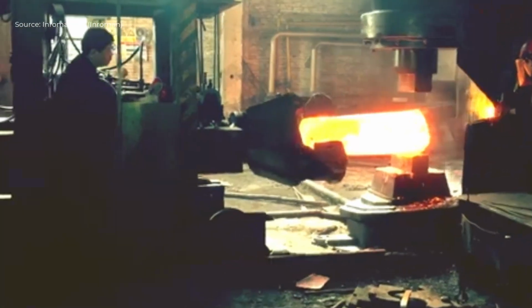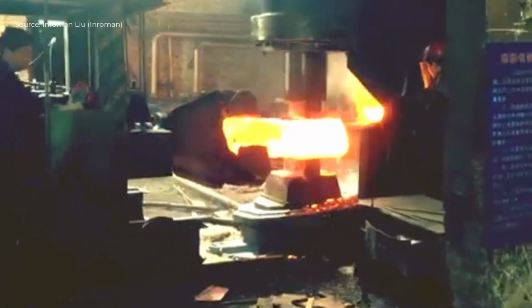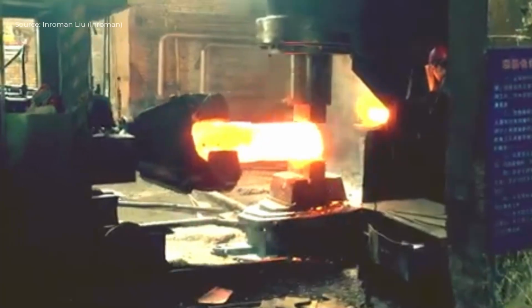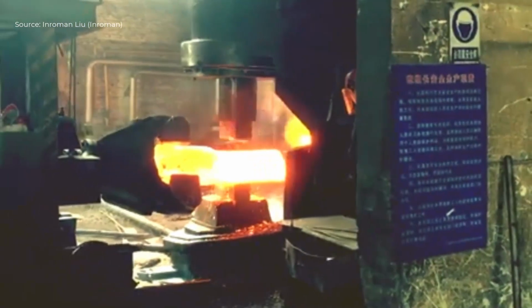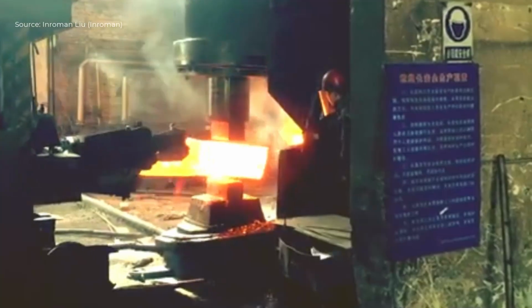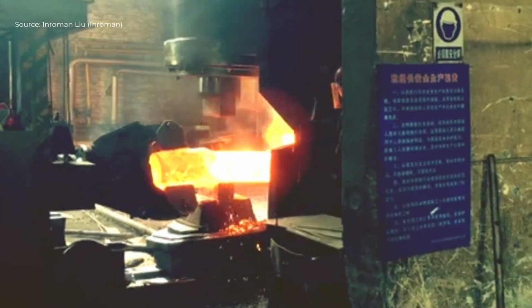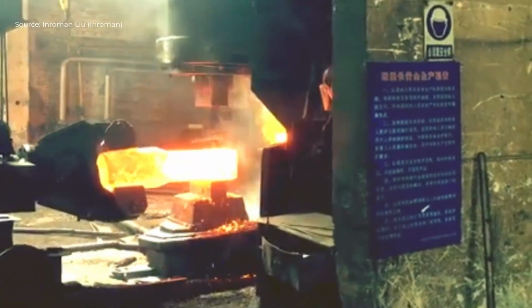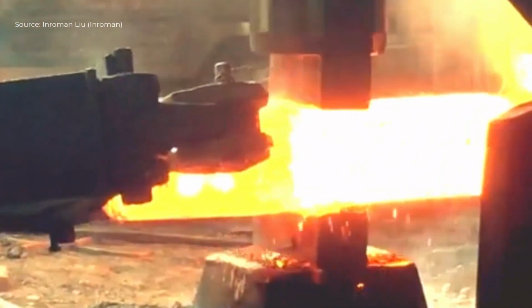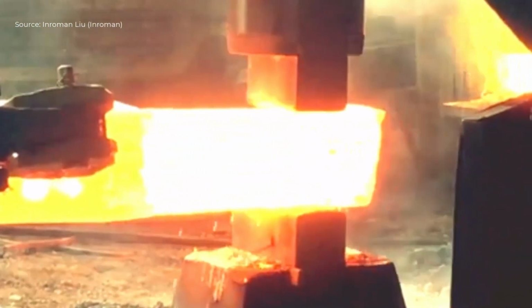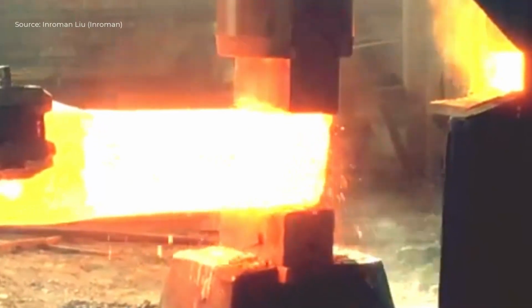The forging starts with billet forging, where the ingot is compressed between flat dies to reduce its cross-section and extend its length. This open die forging stage improves the internal grain structure and eliminates porosity. The workpiece is rotated and repositioned repeatedly to ensure uniform deformation along all axes.